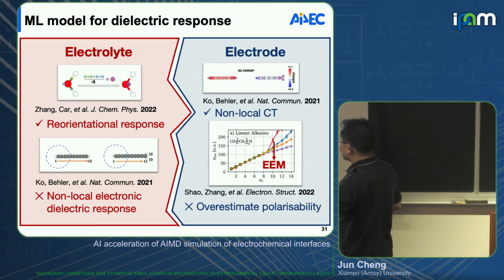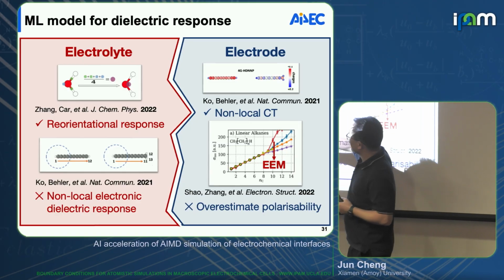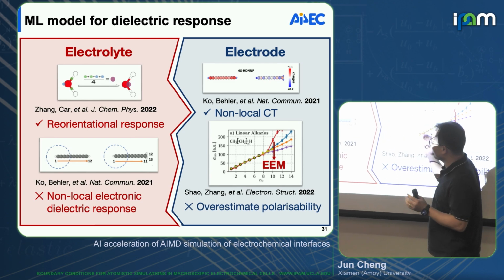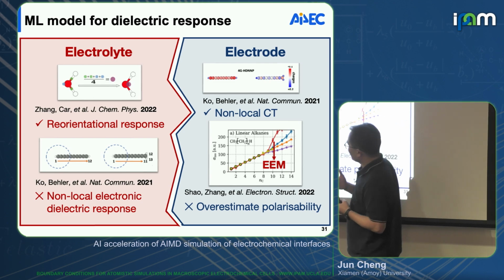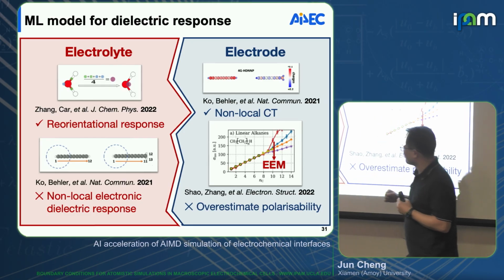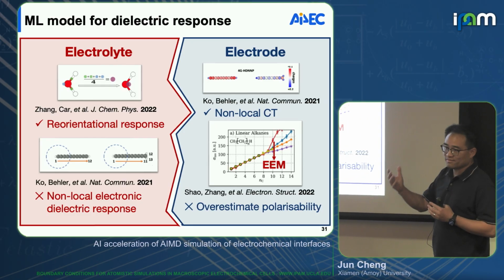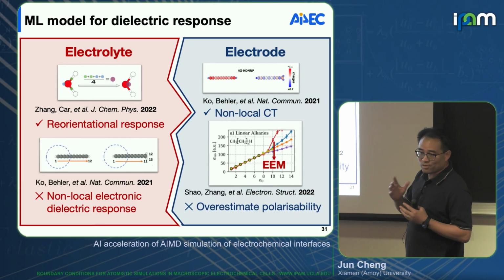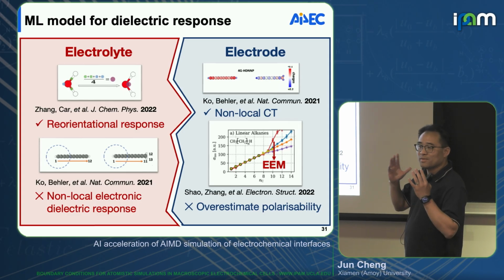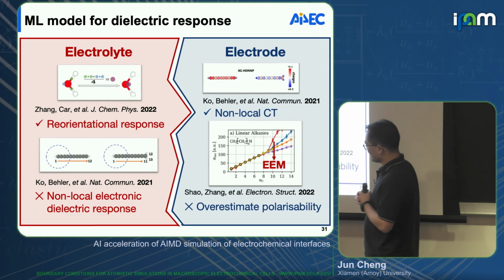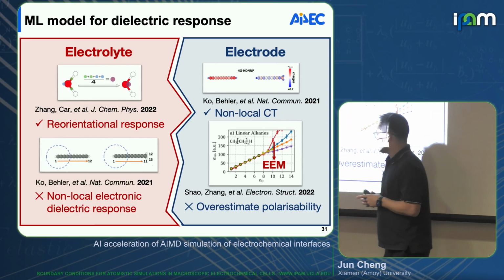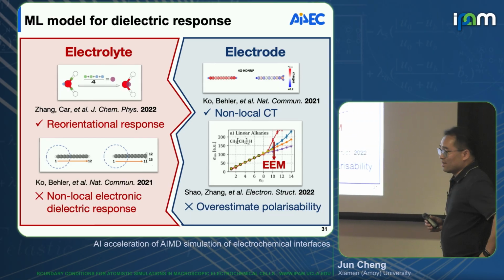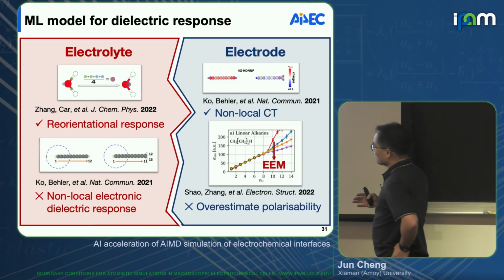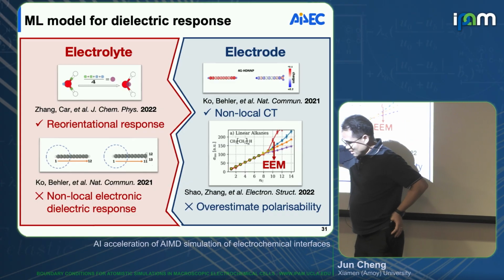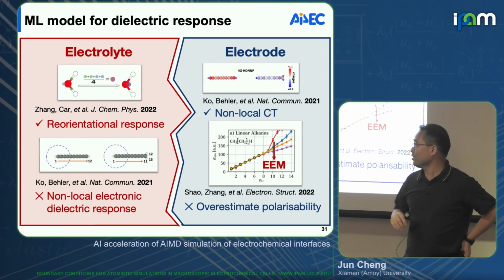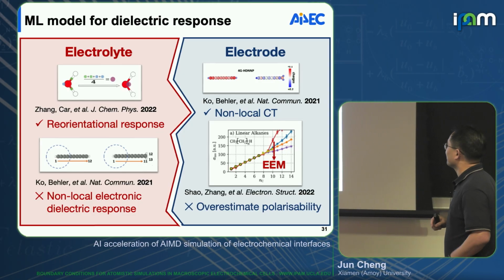For the electrolyte, like Annabella showed, using the so-called Deep Wannier, you can use the Wannier localization, right? You get the Wannier centers. You can predict the Wannier centers using a neural network. Then you can treat the polarization by summing up all the Wannier centers. But it's not taking into account the long-range electron response, not for metal, and also not for aromatic organic molecules where you have a delocalized pi bond, right?